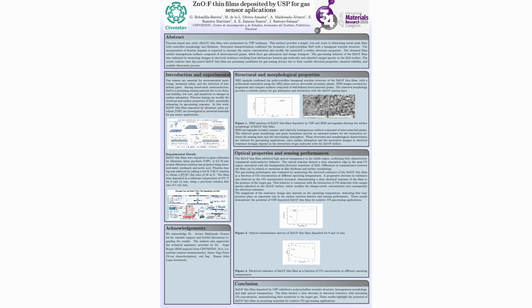The basic sensing mechanism is shown here. When ZnO is exposed to air, oxygen molecules are adsorbed on the surface and capture electrons from the material. When a reducing gas, such as carbon monoxide, interacts with these adsorbed oxygen species, electrons are released back into the material. As a consequence, the electrical resistance changes, and this resistance change is what we use to detect the presence of the gas.